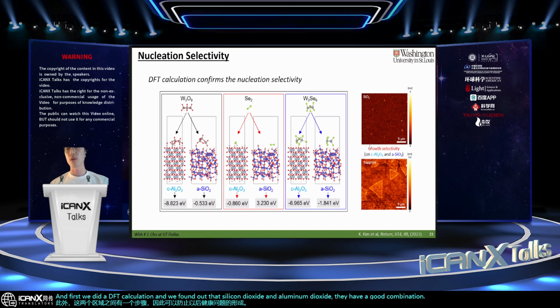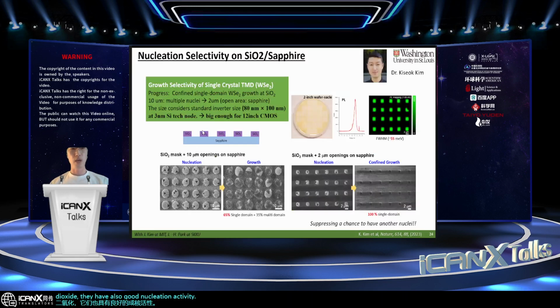Also, silicon dioxide and aluminum oxide have good nucleation selectivity for this purpose. As you can see, we successfully confined the seeding area, but when we have a larger pocket region, it cannot secure a single seed within this target region.